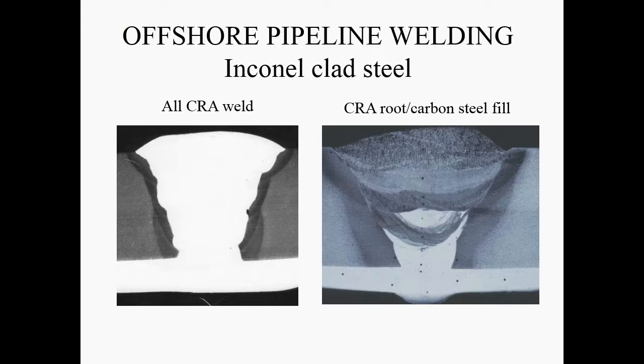Welding the cladded pipelines. So what is this clad? Well, generally all the CRA, the corrosion resistant alloys, based on nickel mostly, they are very expensive. So the clad applies on the inner side of the pipe usually, because we need to prevent corrosion. The corrosion is produced by the hydrocarbons that are transported through the pipe. And generally, you see that's here the clad. So the thickness of the clad is much, much smaller than the wall thickness of the pipe here.